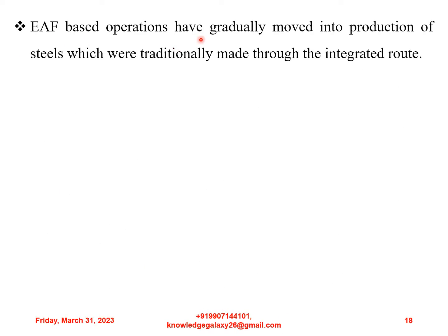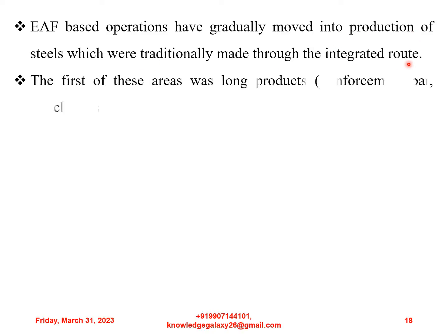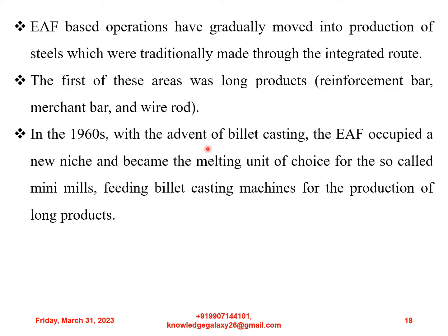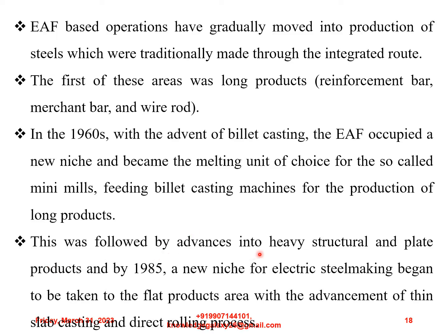Electric arc furnace based operations have gradually moved into production of steels which were traditionally made through the integrated route. The first of these areas was long products, that is reinforcement bars, merchant bars and wire rods. In the 1960s, with the advent of billet casting, the electric arc furnace occupied a new niche and became the melting unit of choice for the so-called mini mills, feeding billet casting machines for the production of long products. This was followed by advances into heavy structural and plate products, and by 1985 a new niche for electric steelmaking began to be taken to the flat products area with the advancement of thin slab casting and direct rolling process.